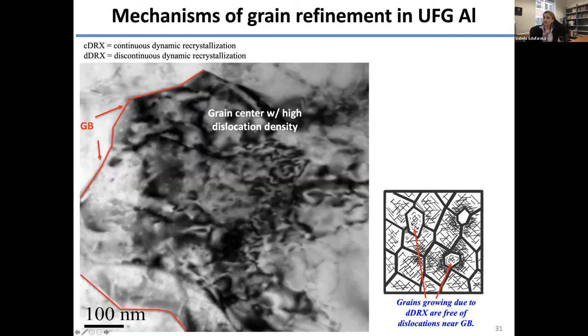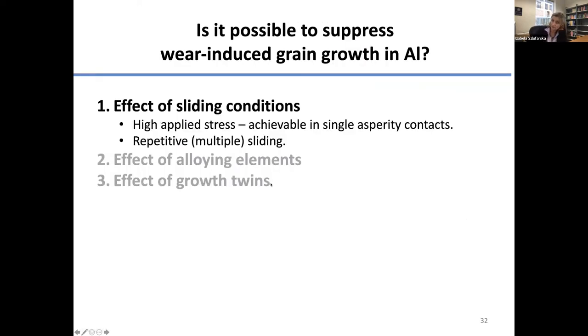I'm just going to show an example of that from our experiments. Here, I added red lines to guide the eye for the grain boundary. Here's the defect-free, relatively free of dislocation region. And you have this higher dislocation content inside of the grain, which is characteristic of this discontinuous dynamic recrystallization. So what we have shown here is that wear-induced grain refinement in aluminum can be achieved for contact stresses that are accessible under practical experimental conditions. And even for lower stresses, grain refinement can be achieved during repetitive multiple sliding if we introduce the defects fast enough.